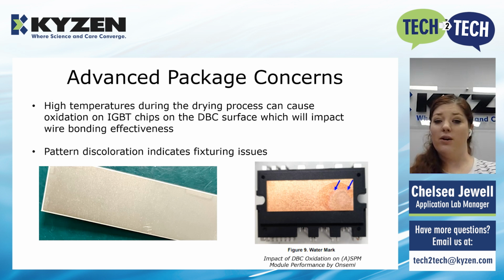There's an appearance factor. You can look in our copper DBC in this image. What they've done is a really, really high heat drying, and it's flashed that water on the surface to the point that you're getting a pattern oxidation as it's going through the cleaning process. So this is going to impact how everything bonds onto that surface in subsequent processes.